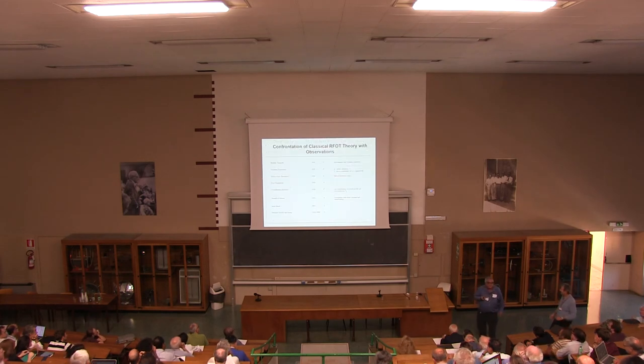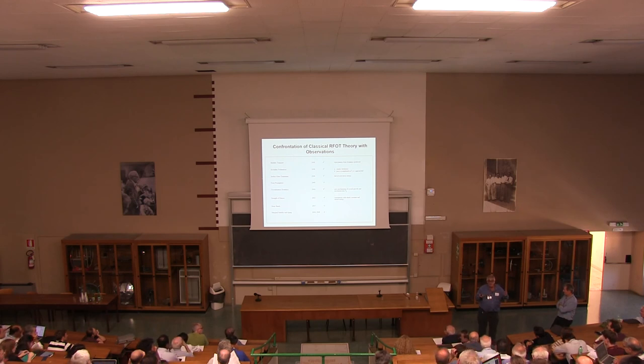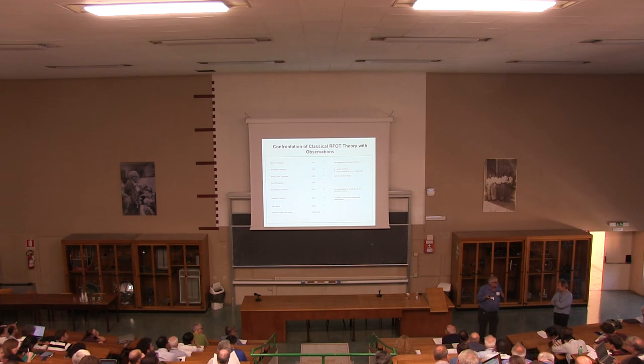One of the things that has come out of the theory that I didn't even plan to talk about was what happens with crystallization. And one of the things which it turns out I had forgotten was predicted in the 1989 paper was that the correlation length for the glassy rearrangement goes larger as you cool, whereas the correlation length for nucleating the crystalline solid shrinks. They cross at some point. When they cross, you get a new mechanism of crystal nucleation, where crystal nucleation is faster than the alpha relaxation. So in that regime, it's metaphysics to discuss the alpha relaxation. So asymptotically, you're protected from getting there by the reality of crystallization.